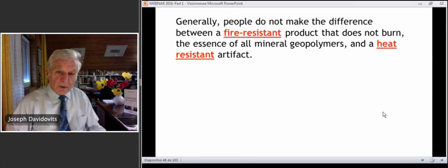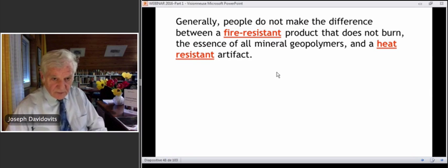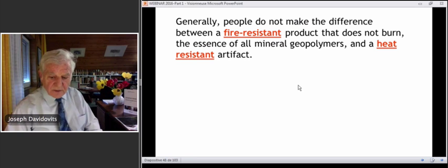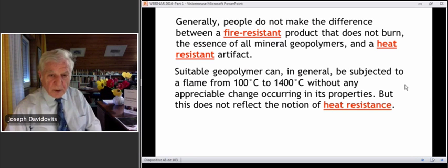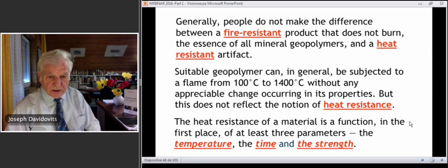Why? Generally, people do not make the difference between a fire-resistant product that does not burn, which is the essence of all mineral geopolymers, and a heat-resistant artifact. Suitable geopolymer can in general be subjected to a flame from 100 degrees C to 1400 degrees C without any appreciable change occurring in its properties. But this does not reflect the notion of heat resistance. The heat resistance of a material is a function, in the first place, of at least three parameters: temperature, time, and strength.